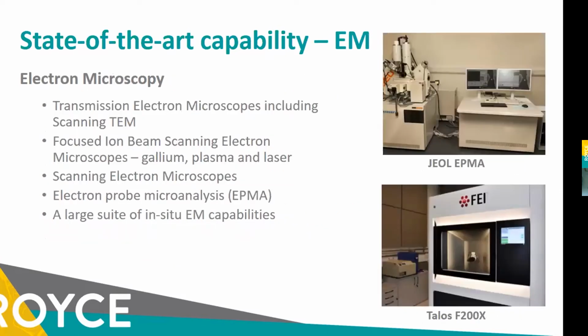So looking now at our electron microscopy equipment, we've got a huge range of EM capability across the different partners in Royce. So with SEMs, TEMs, including the STEM, these have got EBSD, EDS, EELS, as well as in situ capability, including environmental cell holders for heating and biasing, and in situ SEM nanoindentation as well. So we have a Hysitron PI indenter, which allows us to perform quantitative nanomechanical testing while also simultaneously imaging in the SEM. Coupling these two techniques allows the researcher to probe with extreme accuracy and then image that deformation throughout the test, which is really good.